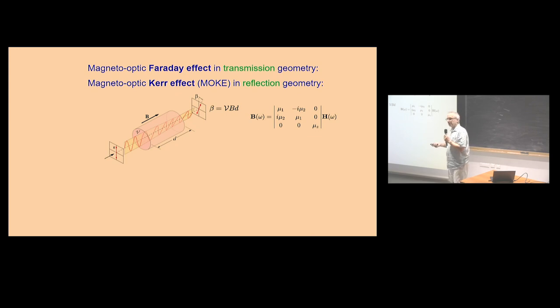I will speak frequently about how to measure magnetic moment in these systems, and of course you cannot use SQUID or vibrating sample magnetometry. You need something fast, and this is an optical method, the magneto-optic Faraday effect. The principle is that you have a magnetic system, or you apply a magnetic field to the system, and you measure the rotation of an optical polarized beam. If you have a linearly polarized beam, you measure transmission and see a rotation of the polarization. This angle is linearly proportional to the magnetic field or magnetization in a ferromagnetic system and the thickness of the sample, and the constant is not important here, although sometimes it is important how strong the effect is.